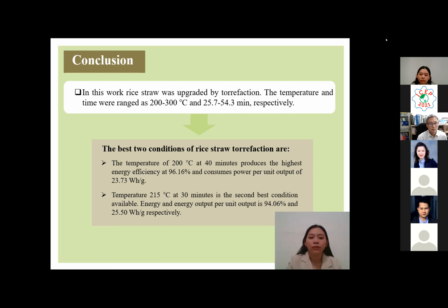Based on the results, it was finally concluded that the highest energy yield of 96.16% and lowest specific energy consumption of 23.73 watt-hour per gram were achieved at 200 degrees Celsius and 40 minutes, while the second best energy yield and specific energy consumption of 94.06% and 25.5 watt-hour per gram, respectively, were obtained at 215 degrees Celsius, 30 minutes. Thus, these two conditions were suggested for rice straw upgraded via torrefaction.